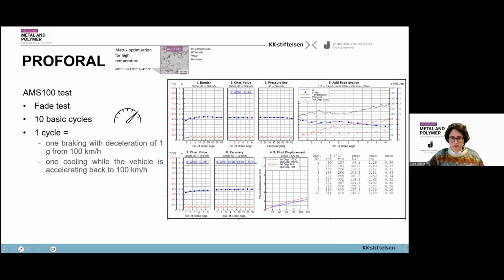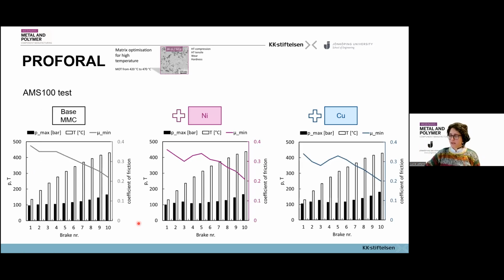If we briefly look also at the AMS 100 test, that was the fade test where we have 10 basic cycles, so 10 applications of braking, following the temperature development due to friction. We can see that in this case also, as we saw before, the base material had a constant performance until the fourth application, and then a constant decrease of coefficient of friction related to the increase in temperature.